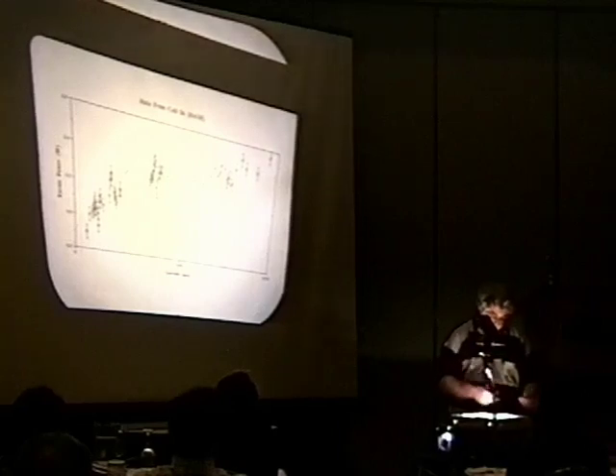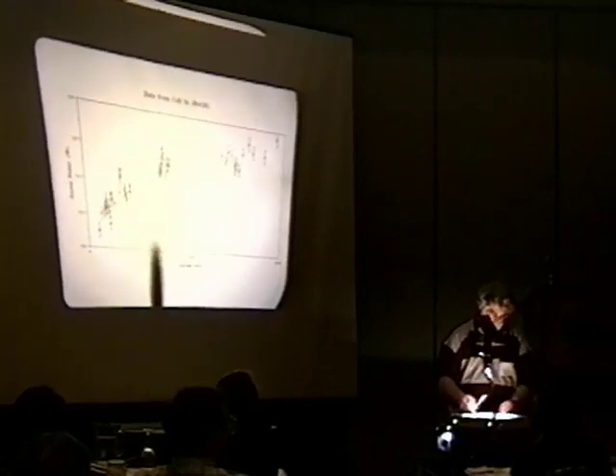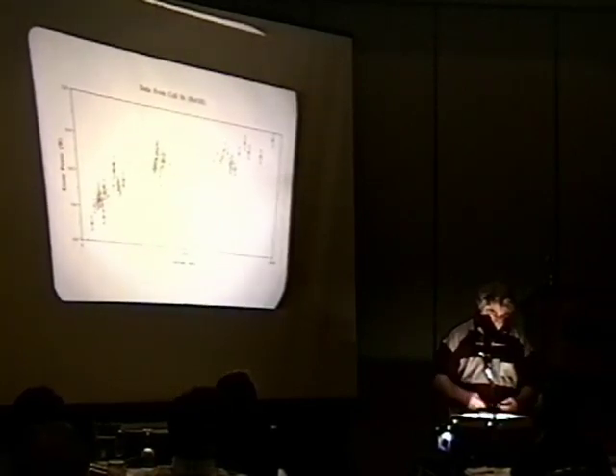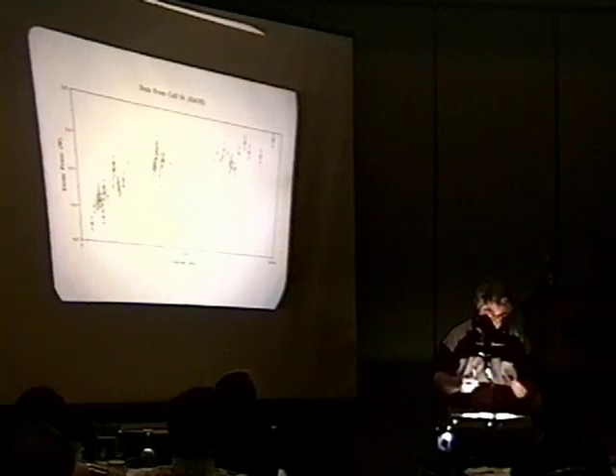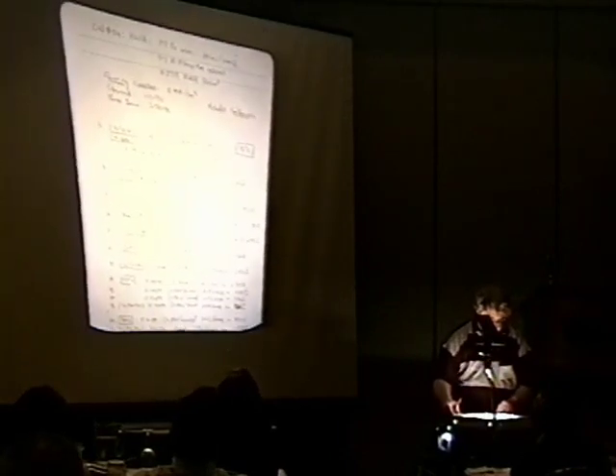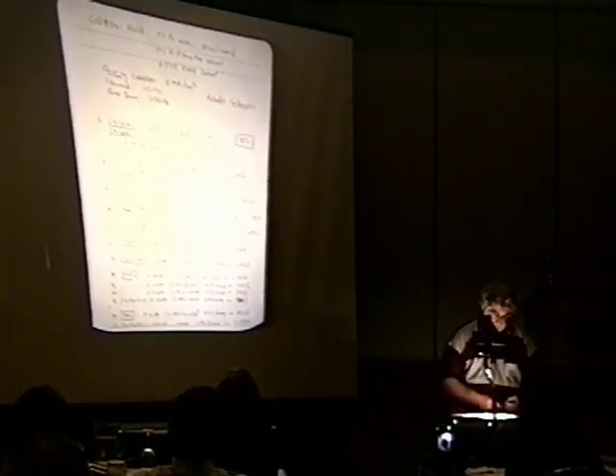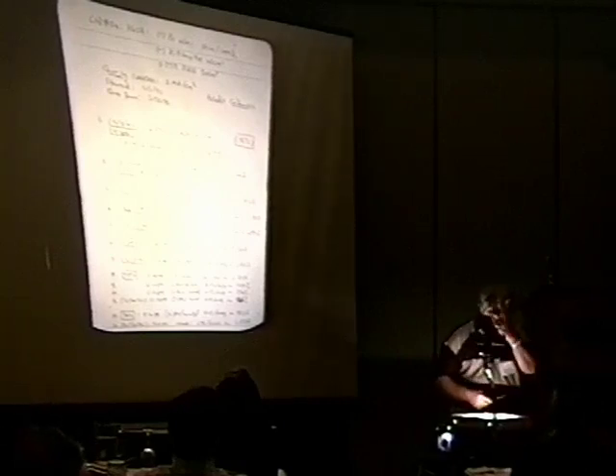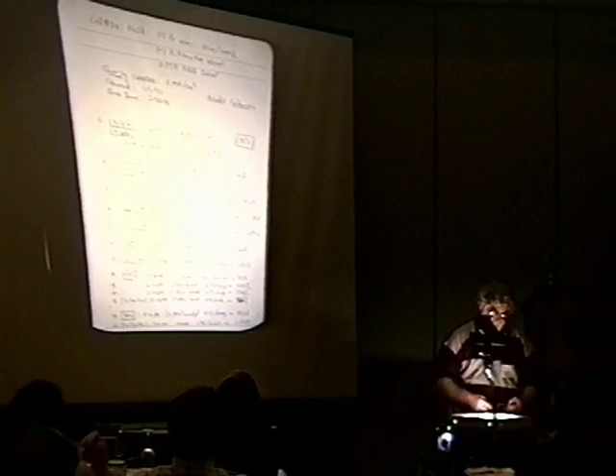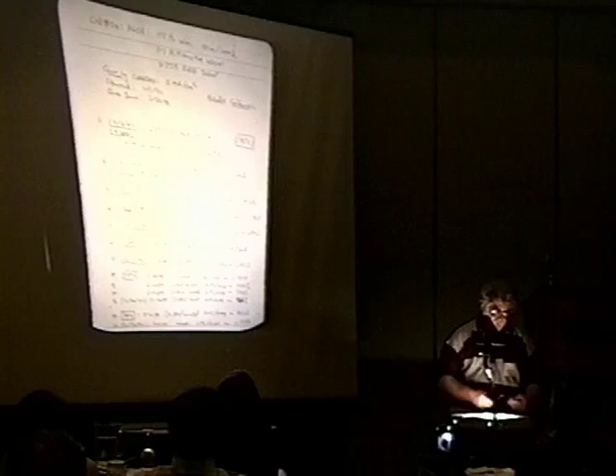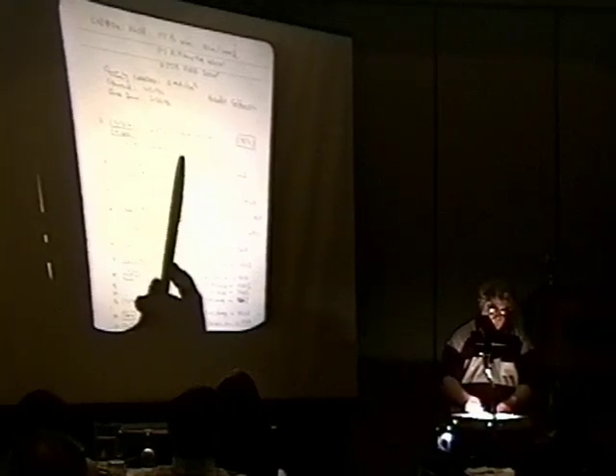We need to go back and see whether that's the case, or see whether we can get this kind of resonance structure. Here they are all on one curve. See if we can get this without the added heavy water. It isn't clear that we can. Okay, now some of you have heard of some fantastic gains achieved with the light water, and that's true in our case. And I want to point out that these have been achieved at very, very low input powers, typically say 1/10 of a watt type thing.